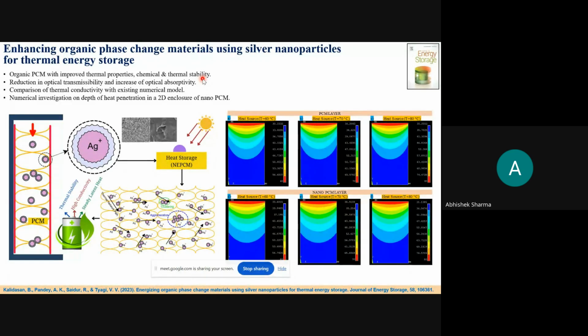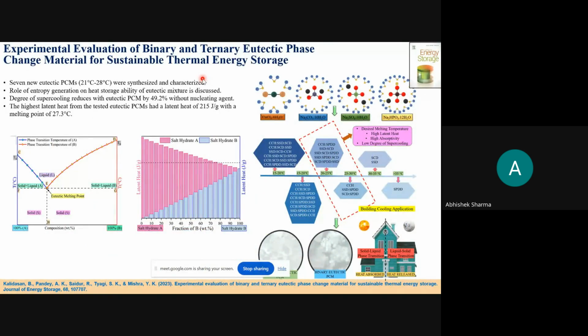Because you are infusing one material into another material, it should be chemically stable. So it was chemically stable. Second thing, it should be thermally stable also. Why is it important to be thermally stable? Suppose any PCM or nano PCM you are coming out with has a melting temperature of 50, and suppose it starts degrading at 50 or 51 degrees centigrade, and you are going for an application where the temperature range is between 50 to 60 degrees centigrade. What will happen as the temperature goes more than 50 degrees centigrade? It will start losing the material. It will start dispersing. So you need better thermal stability of the nanomaterials as well, apart from the thermophysical properties.